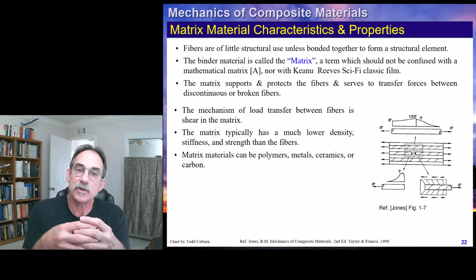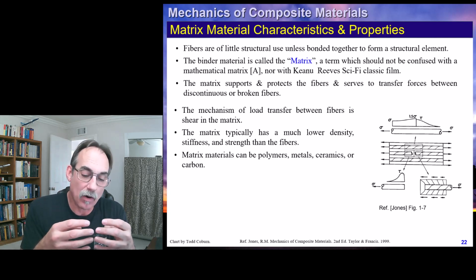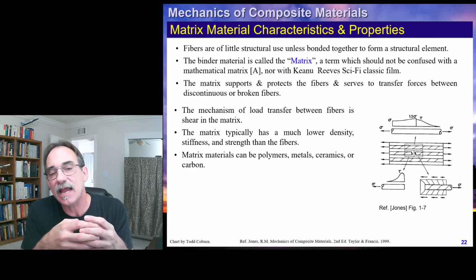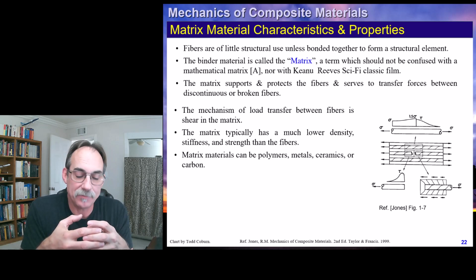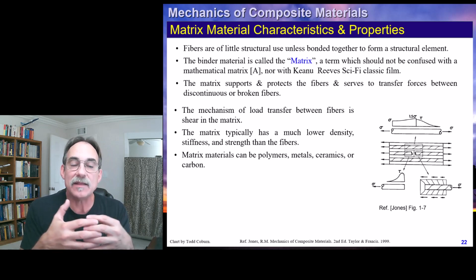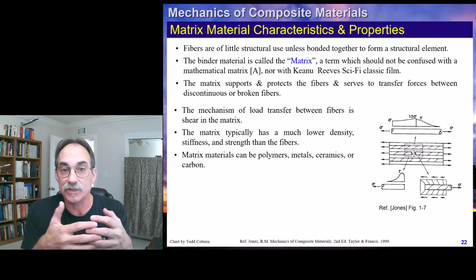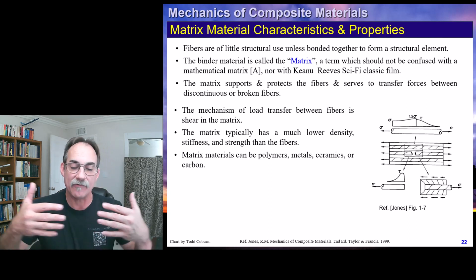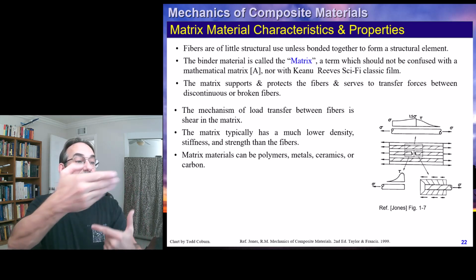So actually we have defects everywhere. Because there are defects everywhere where these little ends are, when we get damage like a cut fiber, it doesn't really change the properties much a lot of times, because the properties that we've been measuring already have a lot of discontinuous spots in the fiber. Now what happens when we have continuous fibers with one fiber that's now discontinuous like we see here?